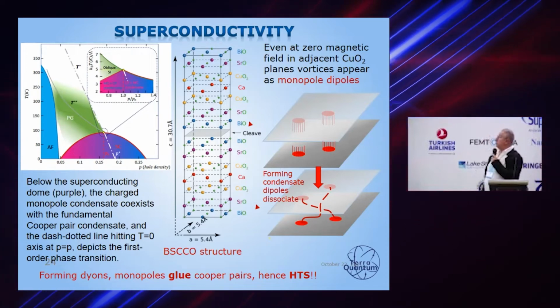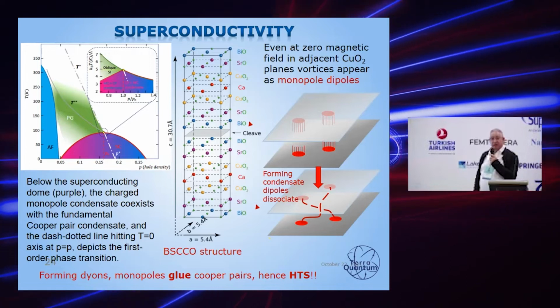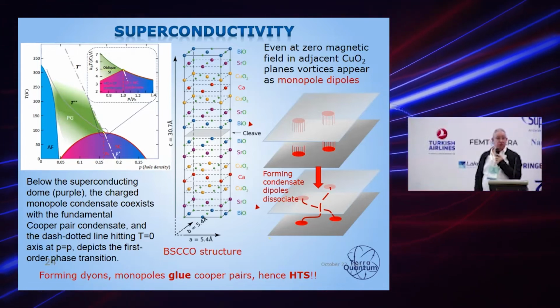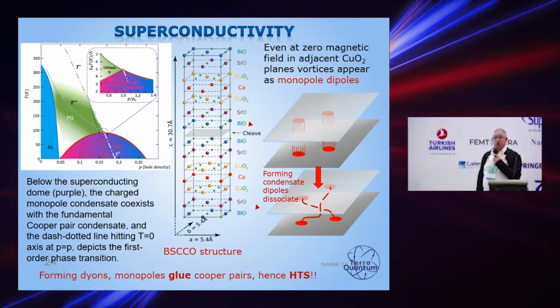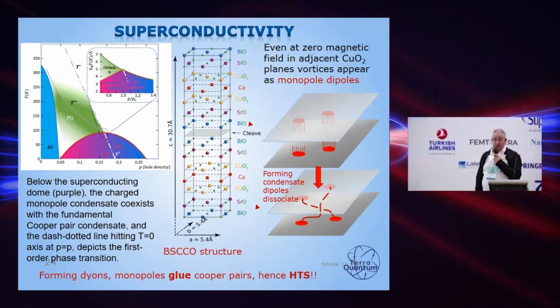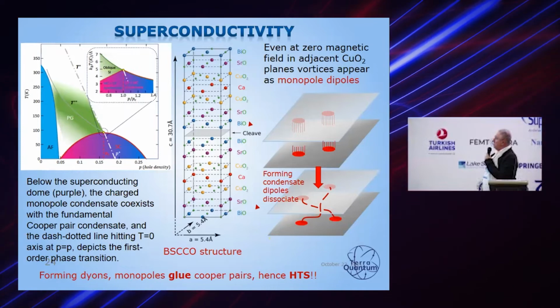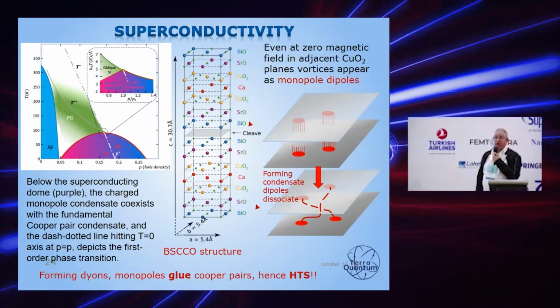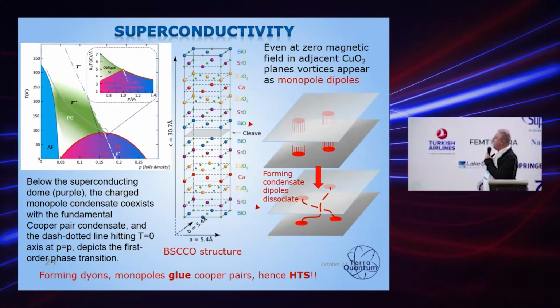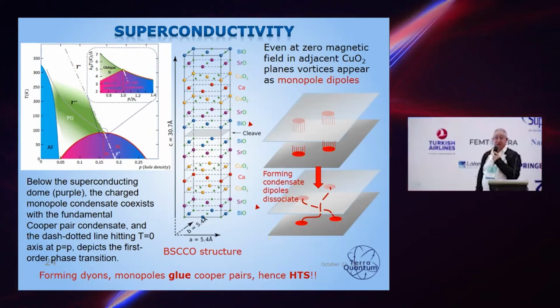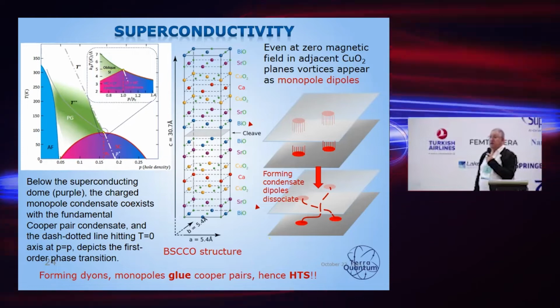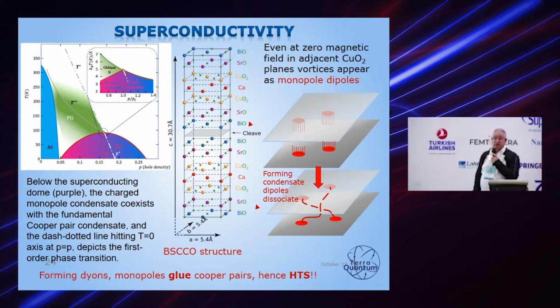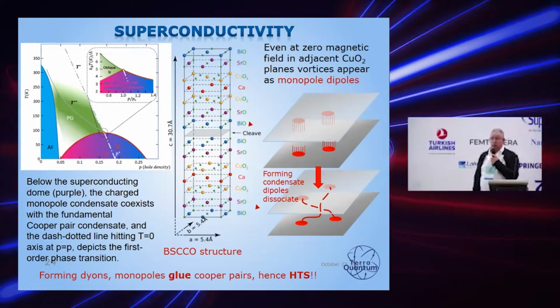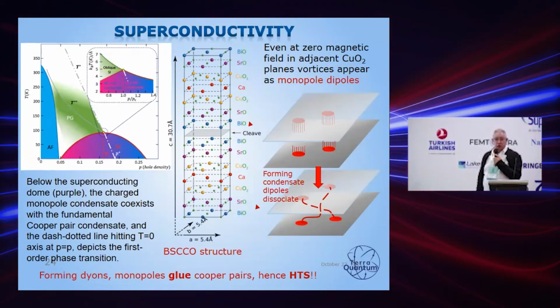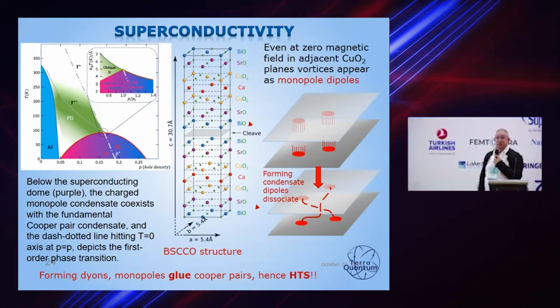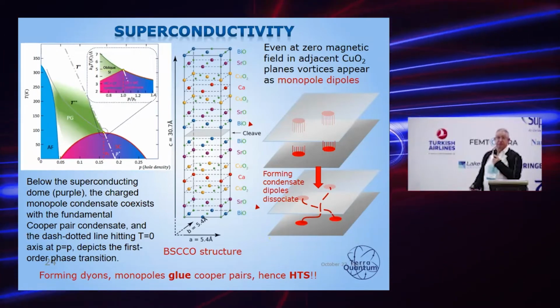And you can immediately remember, for example, that the elementary cell of any high temperature cuprate actually has two copper oxide planes. And this is exactly what we need for this three-dimensional behavior, which is described by the monopole action. So in terms of the microscopic physics, we do have three-dimensional behavior, all right. Now we can immediately say, this is the first stage of understanding, why our superconductors are high temperature superconductors. Because these dyons, or monopoles if you wish, play the role of the glue which makes Cooper pairs stronger. It's just like some additional thing which prevents the splitting into single carriers.